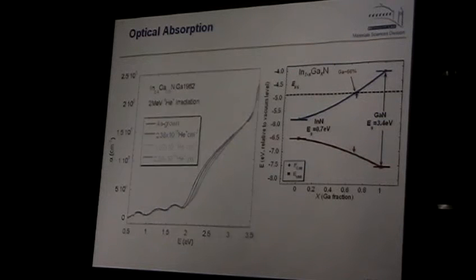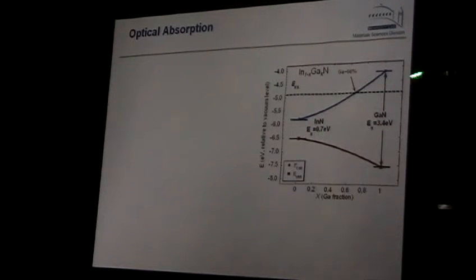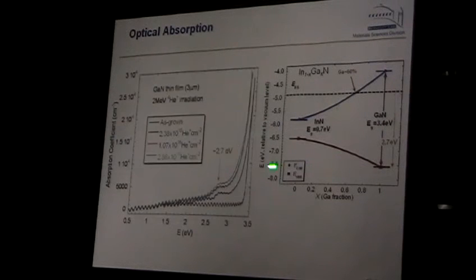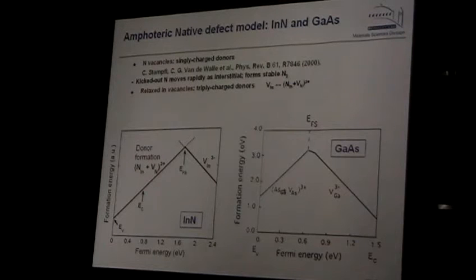And eventually we go to gallium nitride, and in this case the band edge doesn't change, because now these states are here. So we see this onset of new absorption from the valence band to the states here. It's completely different behavior at this stage because the stabilization energy is in the band gap. So how do we explain it? Maybe I briefly tell you about this. The way it works is that defects in semiconductors have this interesting property that they can be donors or acceptors. But whether they are donors or acceptors depends on where the Fermi energy is located with respect to the stabilization energy. So this is the valence band edge.